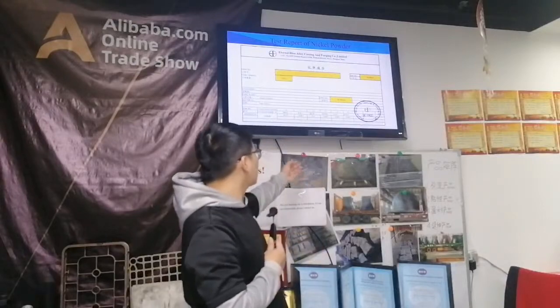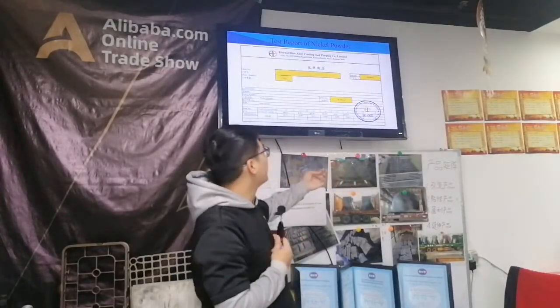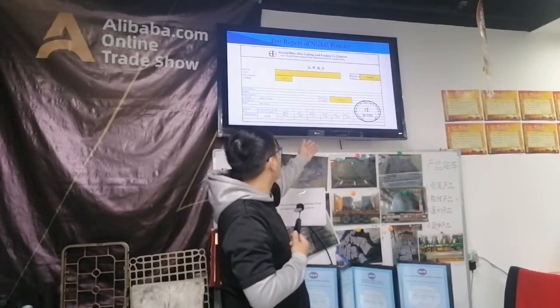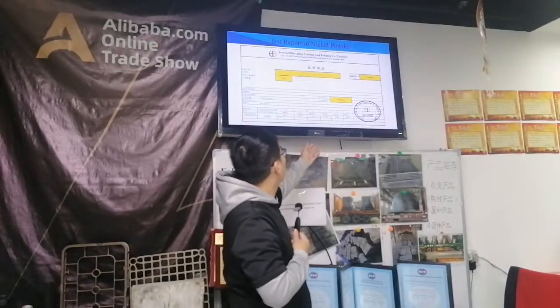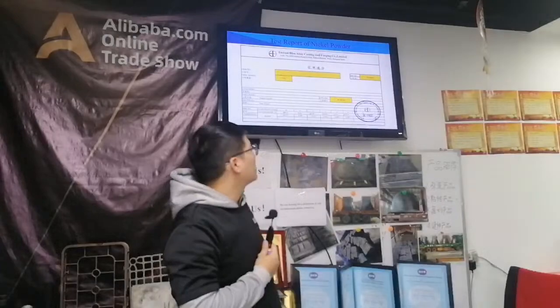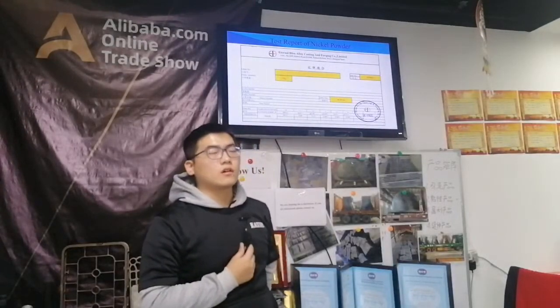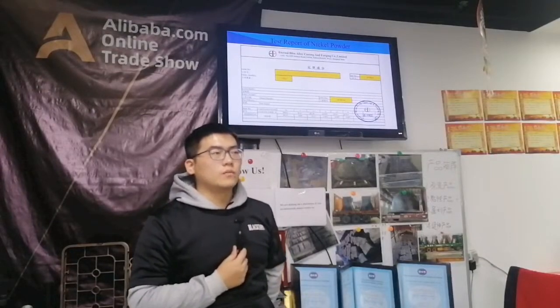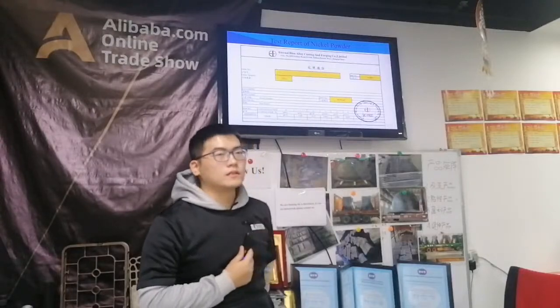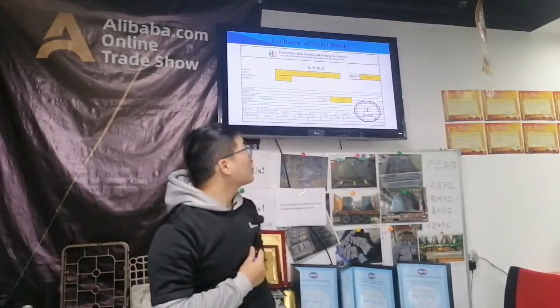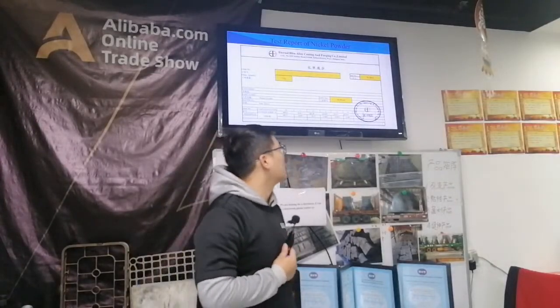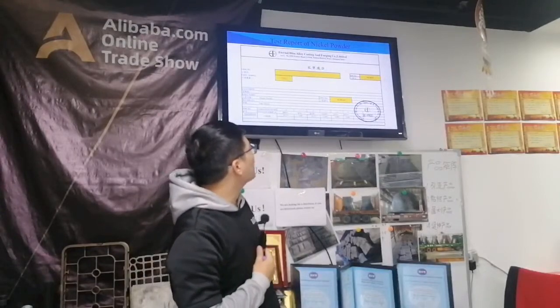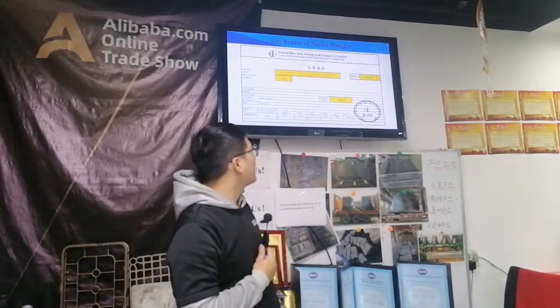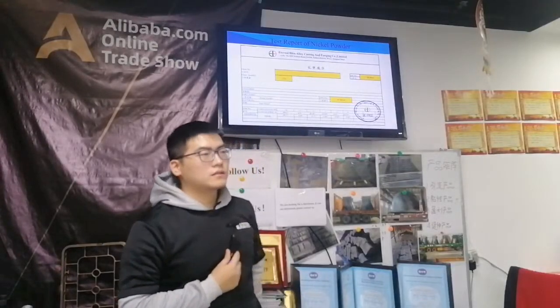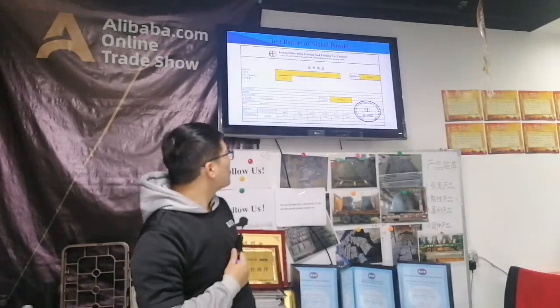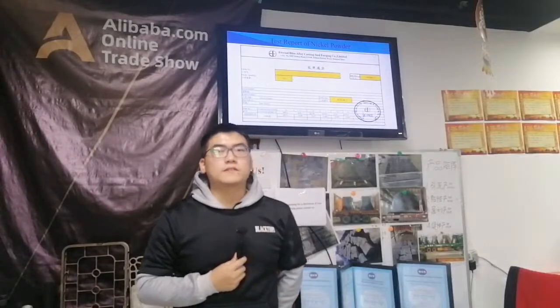As you see, other things, since nickel powder easily oxidizes, you will see the element oxygen takes about 0.13. When you package the nickel powders, it must not be put in a moist environment or moist areas, so it will be oxidized by the oxygen. But the other RE is less than 0.09, so our nickel powders are pure enough.